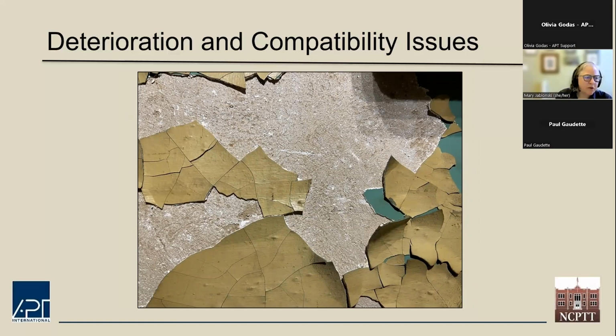Deterioration often happens as well when there's water infiltration into a plaster ceiling that causes the plaster to deteriorate, and it can become quite powdery. Paint does not adhere to damaged plaster surfaces. With some of the more modern paints, there's a problem with vapor permeability. An application of a shellac or varnish over paint can freshen it, but it also makes it impermeable. The impermeable paint traps water that has infiltrated the wall or the ceiling plaster and causes the paint to blister and detach from plaster. Paint will also fail on UV damaged wood, and I can assure you that modern paints do not stick to UV damaged wood.